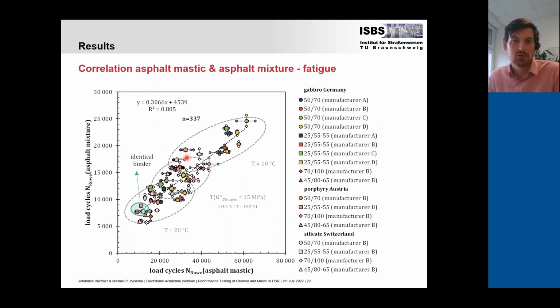The same was done for the intermediate temperature range for fatigue testing. So here on the x-axis, you see the load cycles determined in the DSR for the mastic, and on the y-axis, the load cycles to failure for the mixture. And also here, it's a linear correlation. When the mastic has low fatigue resistance, also the mixture has low fatigue resistance. And at 20 degrees C, the fatigue resistance is lower compared to the lower temperature range here, where we have a higher fatigue resistance. The material is more stiff.